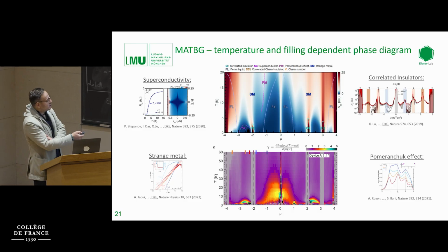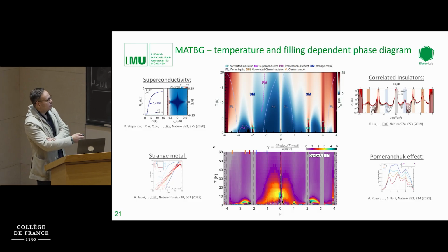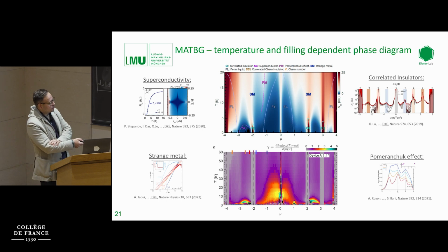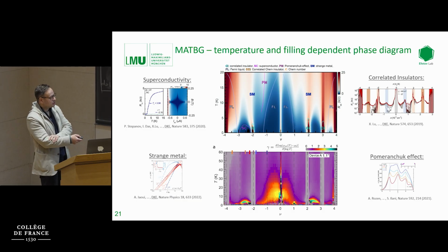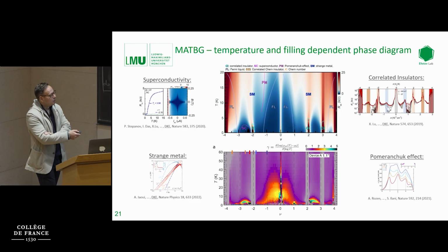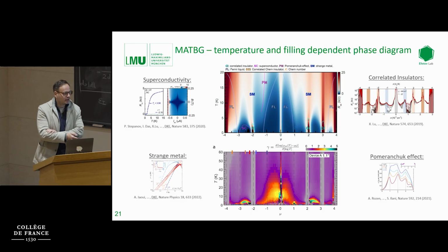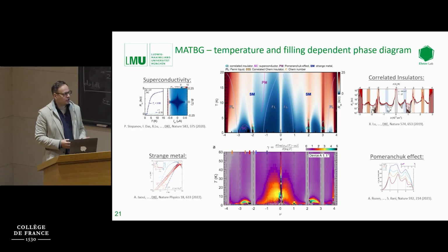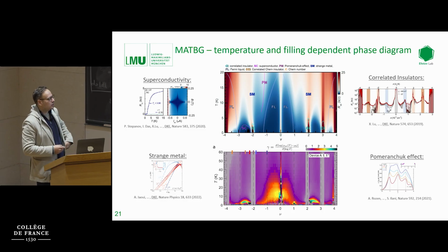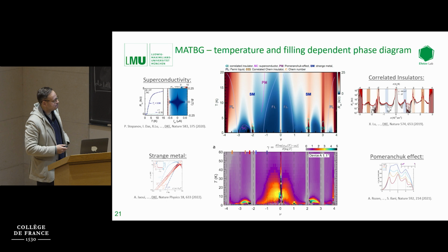Okay, so what you see here in this phase diagram is that the resistance changes many orders of magnitude just when you sweep the gate. In particular, at low temperatures, at integer fillings, we see a number of insulating states appearing: 2, 3, -2 here, which we understand as some sort of Mott-like correlated insulator. Because the U can be bigger than T here, at integer filling we might localize electrons and form Hubbard bands, which give us these correlated insulators.